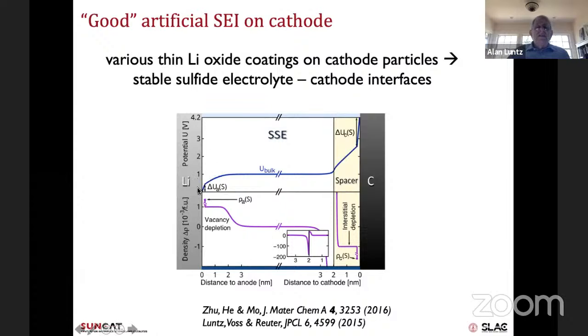Unfortunately, you can't really play the same game with the anode as well, because there aren't many materials that are stable against lithium metal. It's just so reducing. So in that case, you're pretty much limited to what you can do with natural SEI. You can tailor the electrolyte to have a good SEI, and that's somewhat done by chlorinating the sulfides, for example. They form better SEI. Also, what I call wetting agents seem to help a little bit. At any rate, that's all I'm going to say. We'll come back and I'll show you an example in a minute of a very good laboratory scale solid state battery.